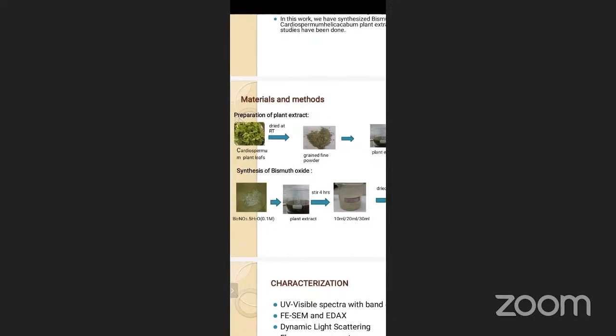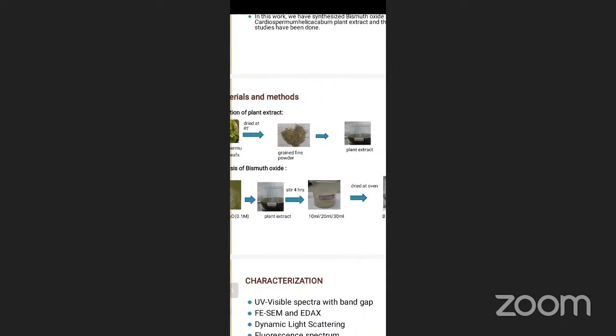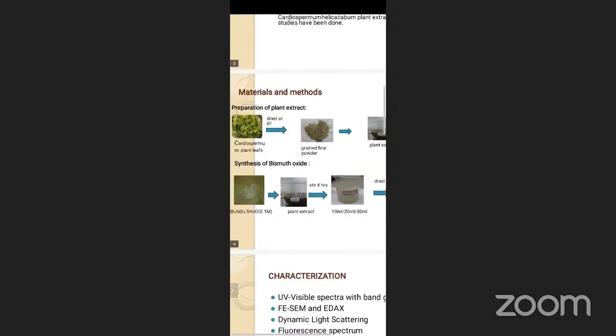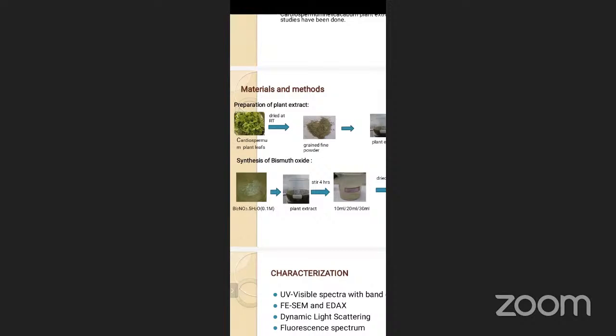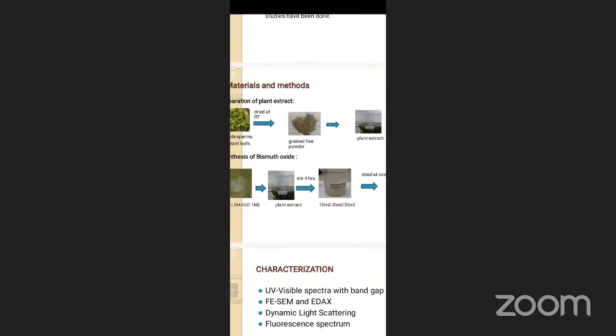Here we take bismuth nitrate pentahydrate as the precursor material for the synthesis of bismuth oxide nanoparticles, at a molar concentration of 0.1 mole. We take different ratios by adding the plant extract: 10 ml, 20 ml, and 30 ml of plant extract, calculated out of 100 ml. For example, if we take 10 ml of plant extract, we add 90 ml of bismuth nitrate precursor.